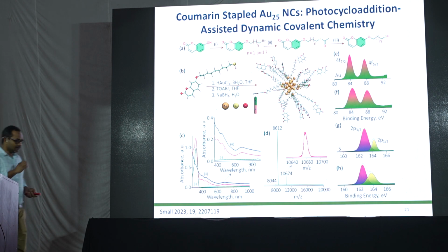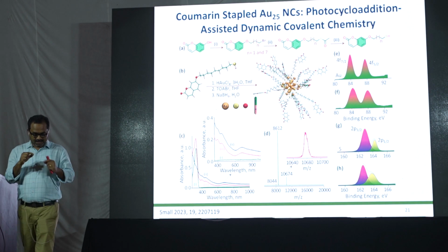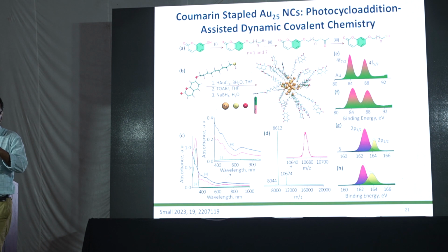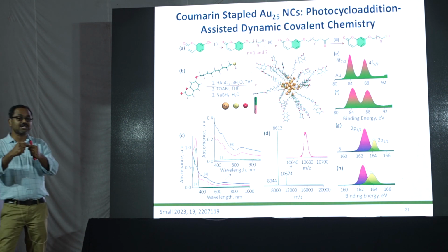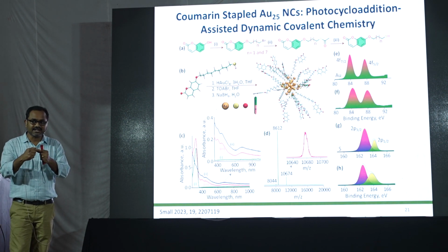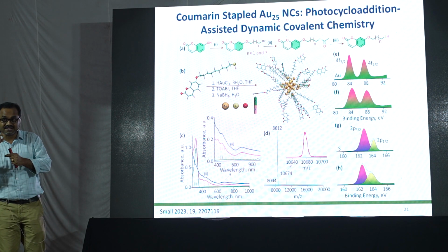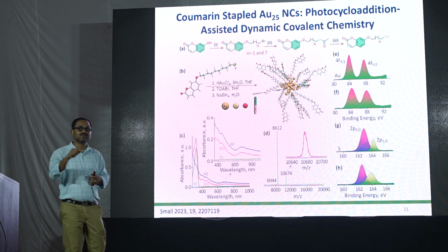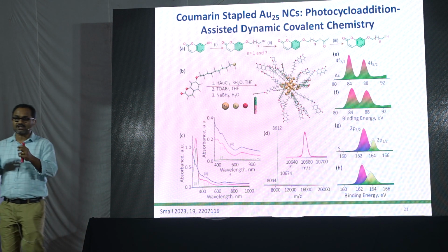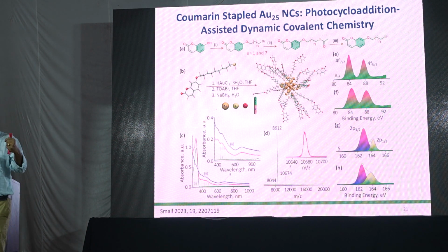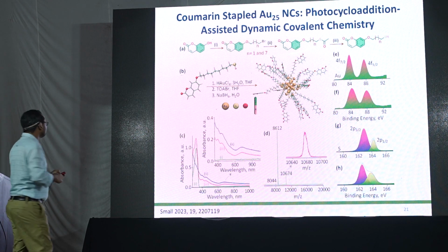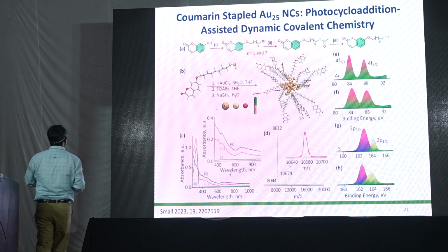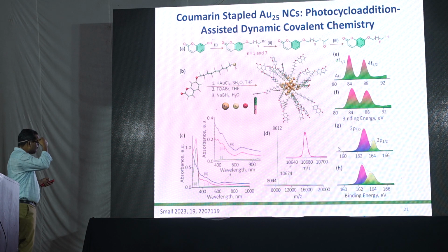And now the question is, in the azobenzene case, there is basically a dipole-dipole interaction. There is no covalent interaction. It's only a dipole-based assembly. So we thought about making a molecule, a chromophore, which can undergo [2+2] cycloaddition, so that means nanoclusters can be covalently connected. For this we have used coumarin molecules, and we made coumarin thiols.